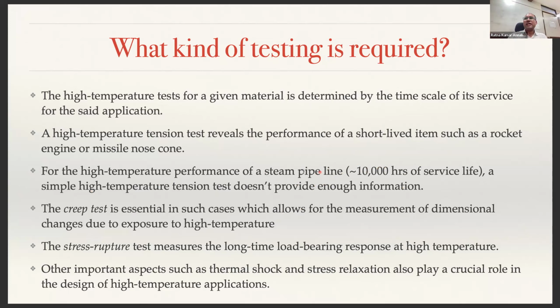In such scenarios, you need to do a creep test, because the creep test allows for the measurement of dimensional changes over a long period of time due to exposure to high temperature. So creep tests typically take very long times. You just apply a dead load and keep it at some high temperature and wait to see whether the extension is happening in the material or not.